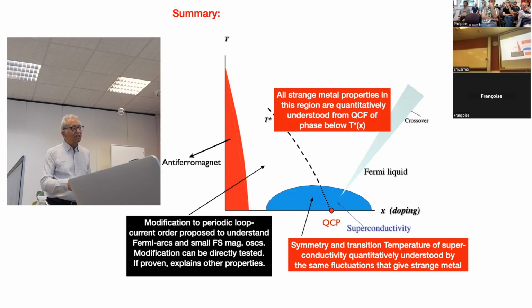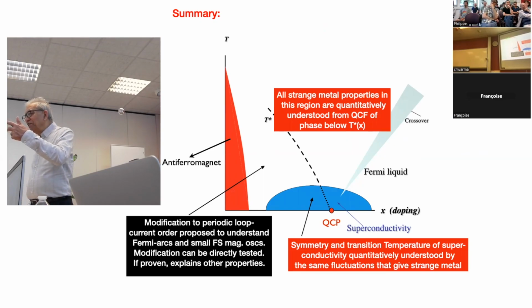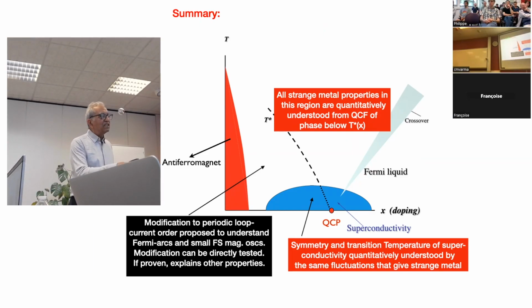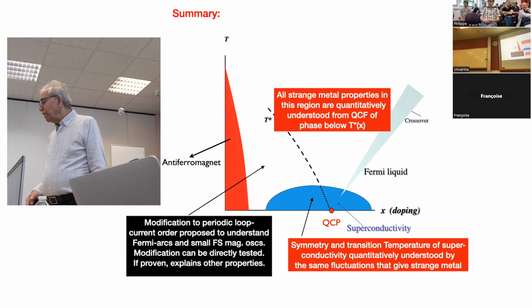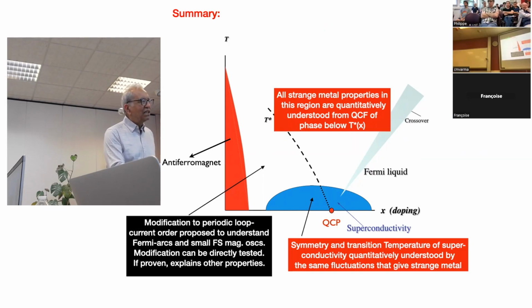So let me summarize my talk. I can honestly say that we understand from the critical fluctuations of the order parameter that I propose here essentially everything here and here in terms of two parameters for many things, and a third parameter, which is the amplitude of the critical fluctuation. You see that is a constant. I need that in absolute units. I can roughly get that from Phys measurement of the magnetic moment. So I can understand things quantitatively in this region, in this superconducting region.